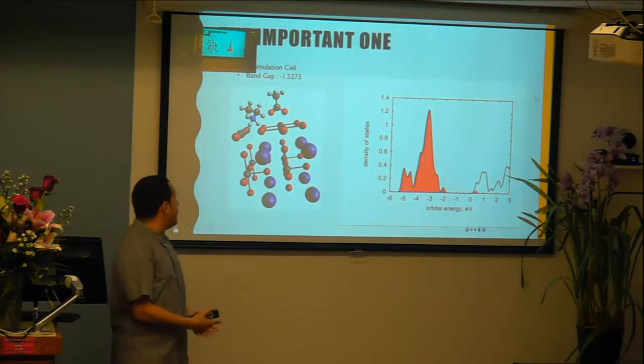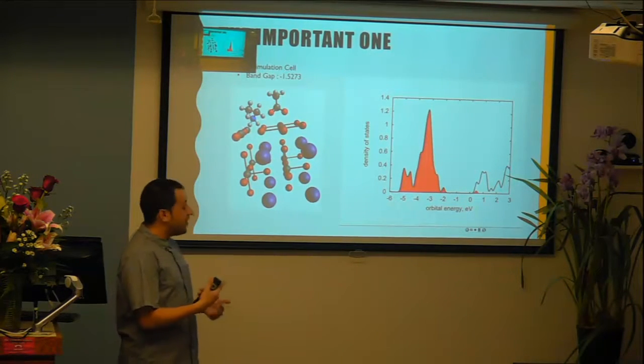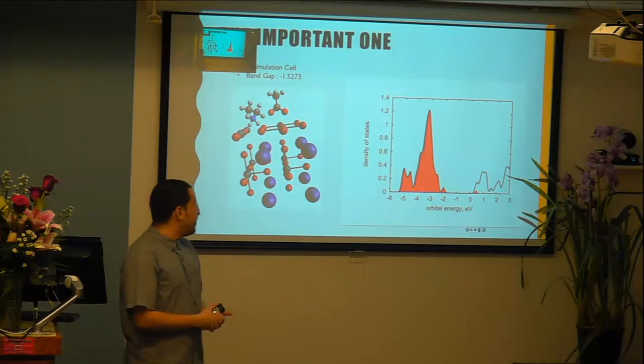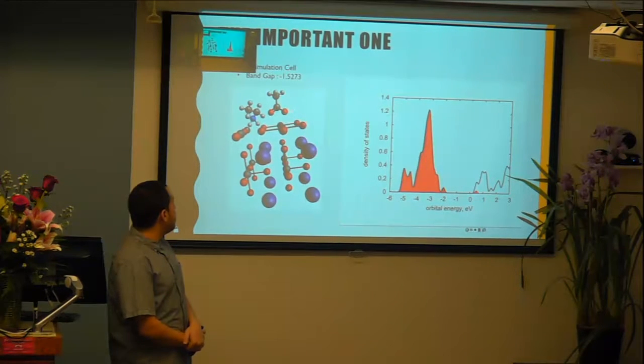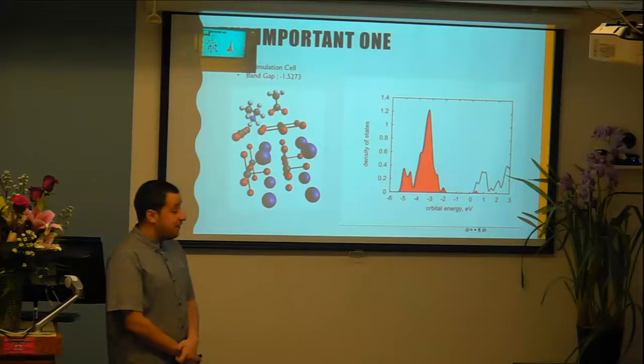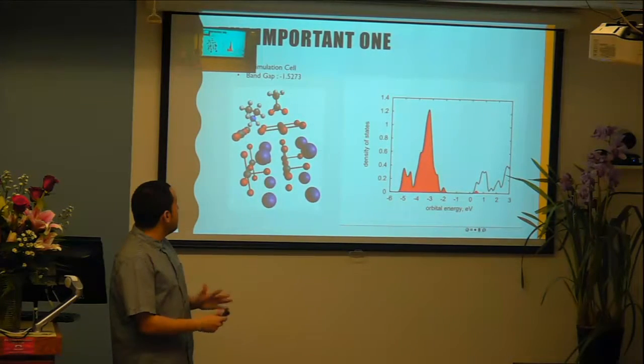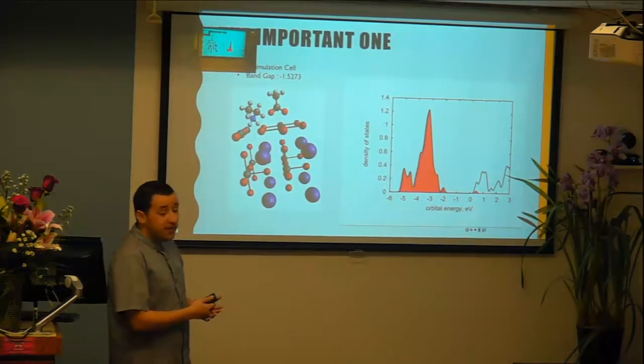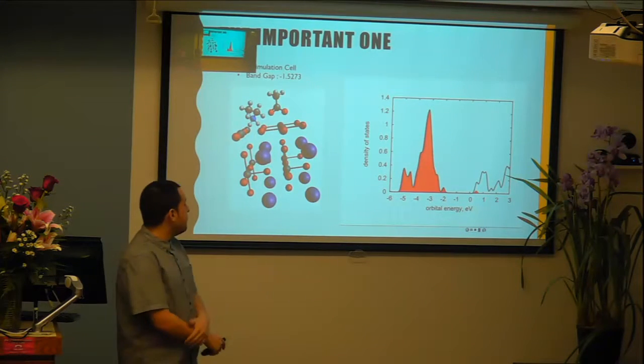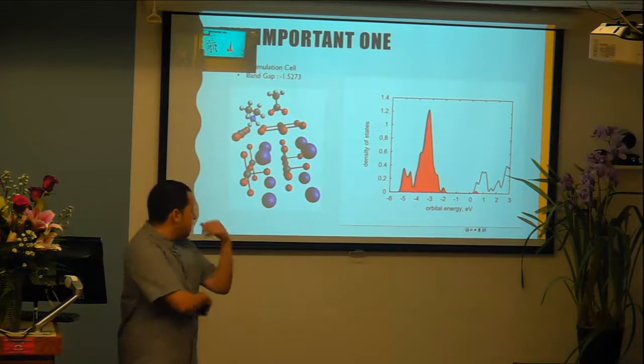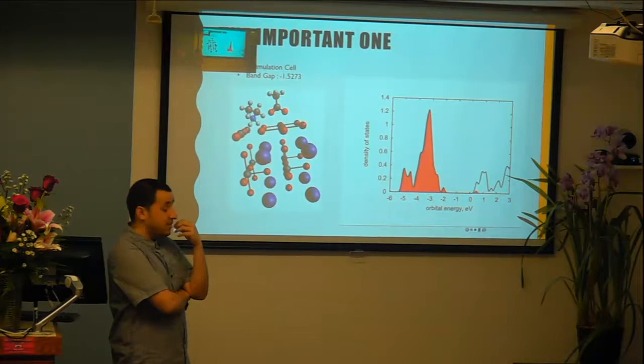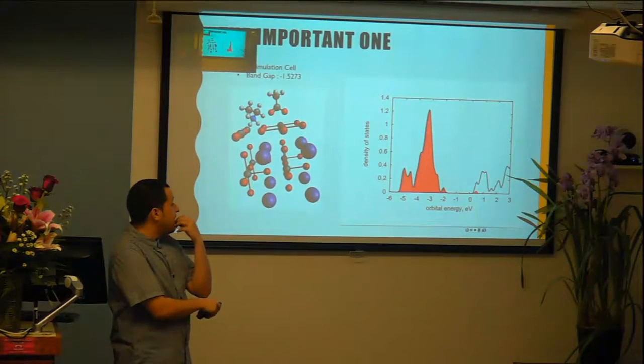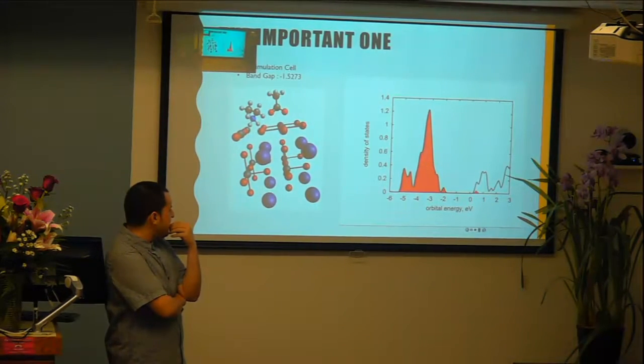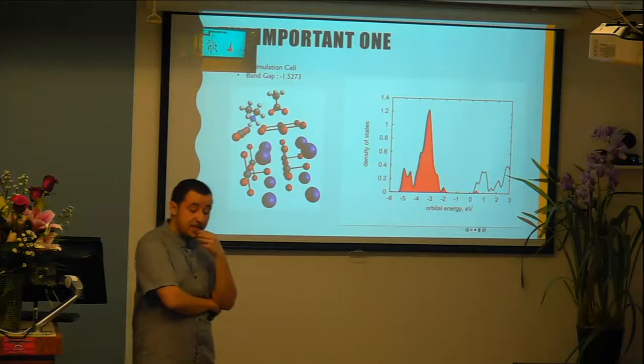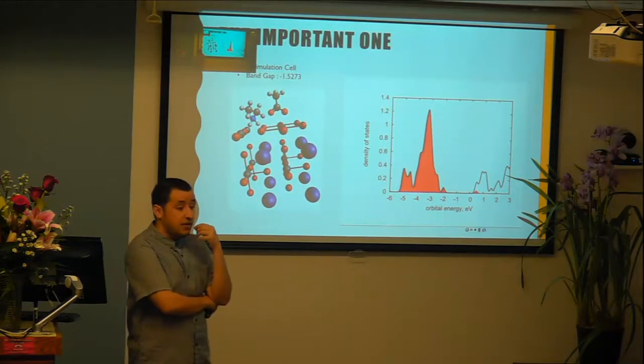The more important one is when we look at both of these together in combination. So whenever we attach our acetate ion and our ethyl ammonium together, we have a band gap of 1.5 electron volts. In our density of states over there, we still see some type of density across the band, but that's probably due to the N-type ligand, our ethyl ammonium.